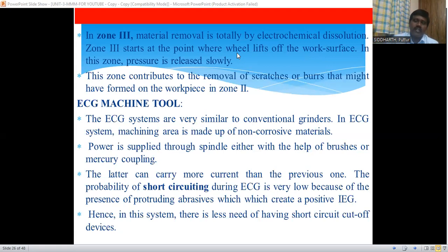While it is going to move in the upward direction, some of the grinding abrasives will touch the surface of the workpiece. In this place, the pressure is released slowly, and there also some of the material is removed purely because of the electrochemical dissolution. This zone contributes to the removal of the scratches and burrs that might have formed in zone 2. So in zone 2, the maximum amount of material is removed. During this machining in zone 2, whatever burrs or scratches are formed because of the sharp edges of the grinding wheel, those burrs or scratches are removed by means of this zone 3.